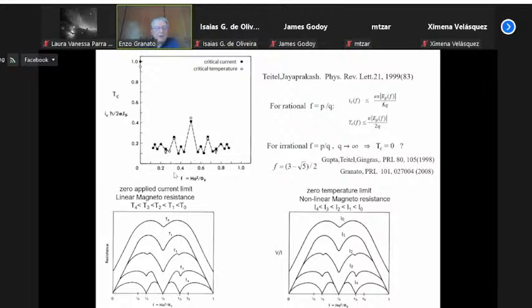On the left here, we show what you would expect for the resistivity as a function of magnetic field, parameterizing the frustration, because the critical current changes rapidly with the frustration. As you decrease the temperature, first you get a minimum at the integer value of frustration. Then you get a minimum at 1/2 frustration, then a minimum at 1/3, and so on. There are more and more minima as we lower the temperature.